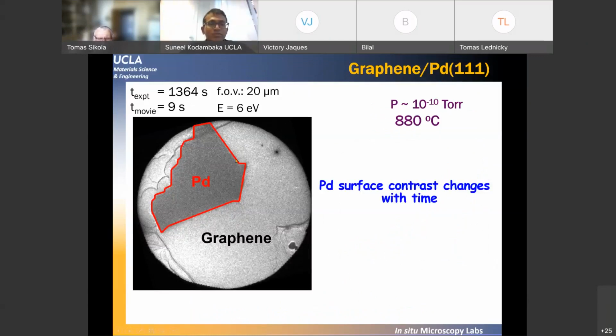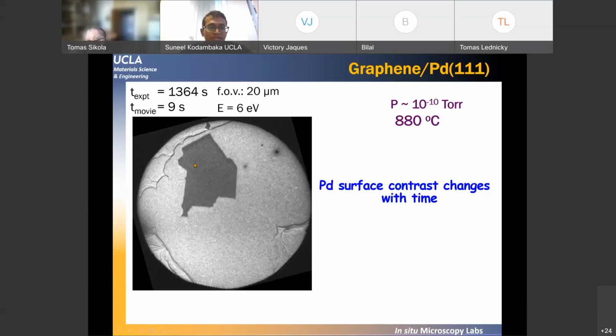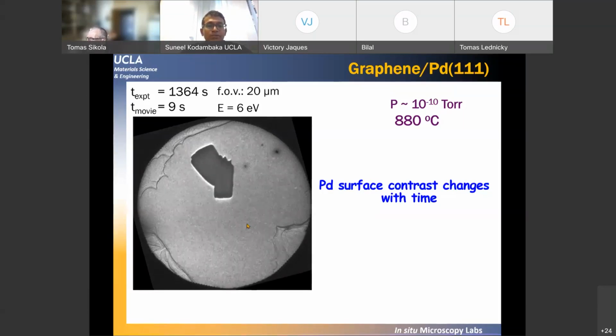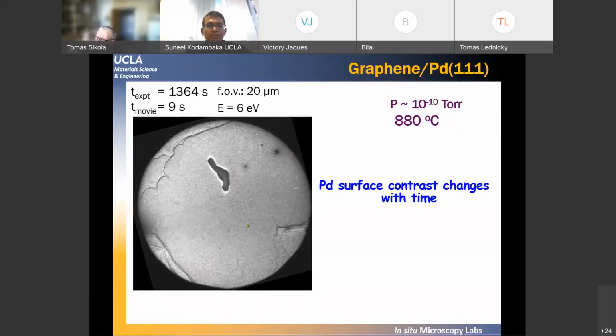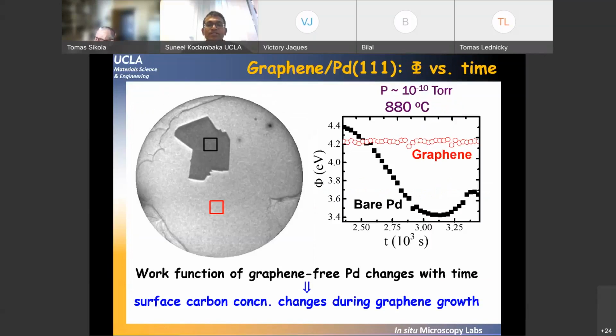Here I'm going to present reflectivity measurements obtained from an area that's not covered with graphene during the growth of graphene. This is the already monolayer-covered graphene, and here you have some leftover palladium that is eventually going to be covered with graphene. Watch the contrast change. This gets darker and darker with time. And so we can now quantify this behavior.